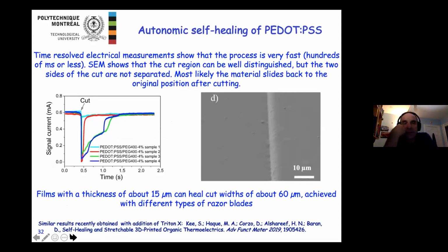Another thing we did, even in this case, was look at SEM. You can see here on the right the SEM image after the cut. You do see that there has been a cut in the material, but the two parts of the material are merged before doing anything else. And again, on the C, you see the time scale, and the process in this case takes place in some tens or hundreds of milliseconds.